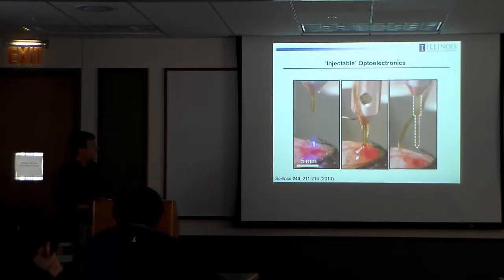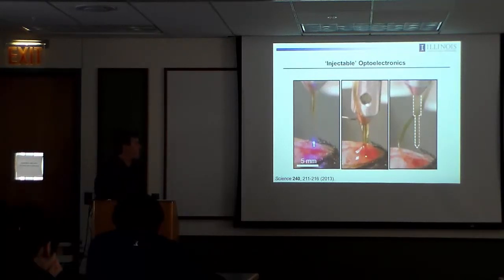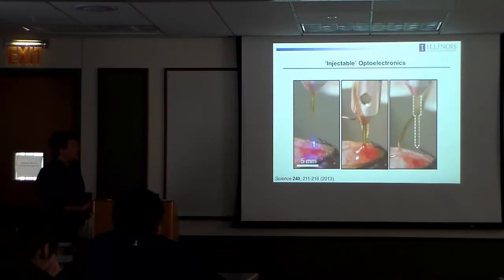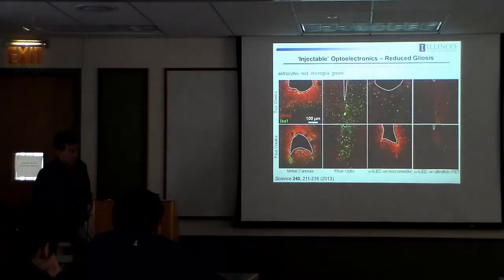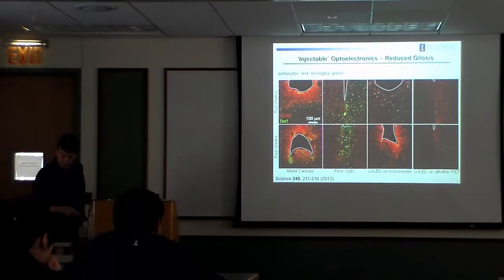Plunge it down into the brain with a computer-controlled stage so you can locate these LEDs specifically in targeted areas of the brain. Once it's down there, we introduce artificial cerebrospinal fluid. That dissolves the bioresorbable glue. It's a silk fibroin material in this case, biocompatible. Once the needle is physically released by that dissolution process, you can pull it back out. So then you just have LEDs embedded down in the brain and electrical contacts emerging from the surface of the brain for connection to external control systems.